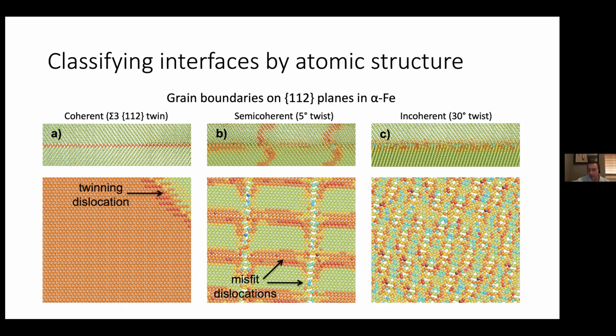You might not say that this boundary is completely disordered, right? So if you look closely, you can probably convince yourself that there's some vestiges of order in there still. But it's definitely not a coherent boundary, and you can't really identify coherent patches that are separated by line defects either. So this is what we would call an incoherent grain boundary.